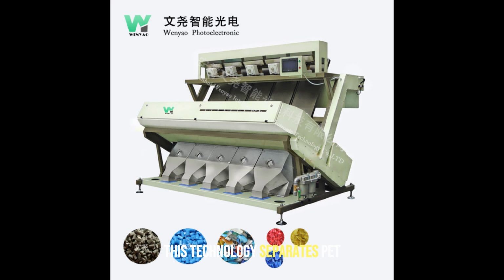This technology separates PET bottles, density 1.38 grams per cubic centimeter, from HDPE jugs at 0.95 grams per cubic centimeter, operating at high speeds exceeding 2 meters per second up to 4 meters per second, while air jets pressurized to 0.5 megapascals accurately deflect the flakes into dedicated collection chutes, achieving up to 95% purity.